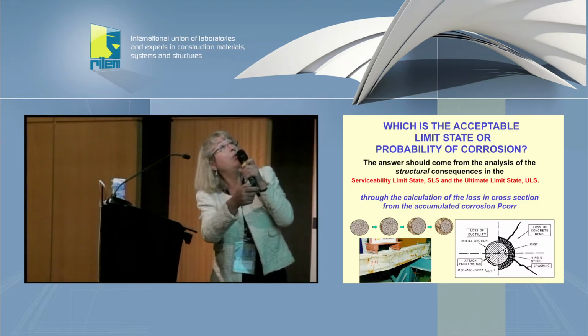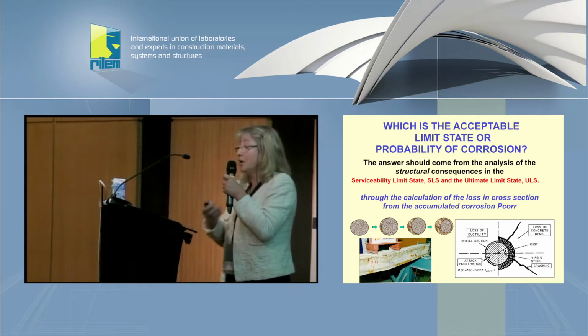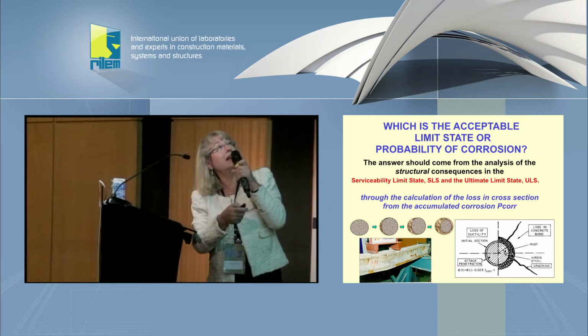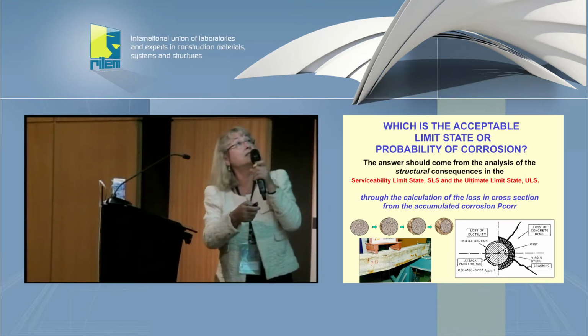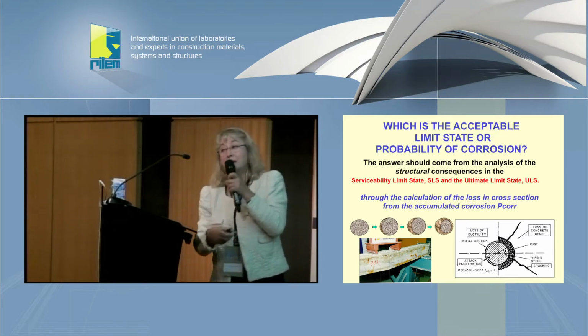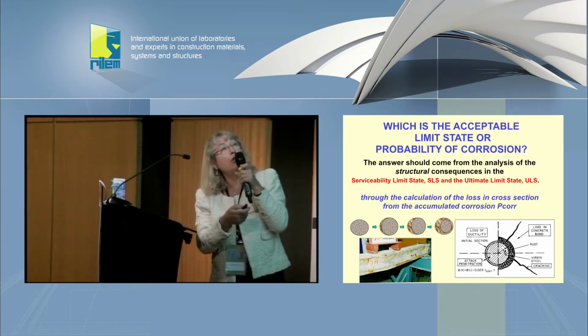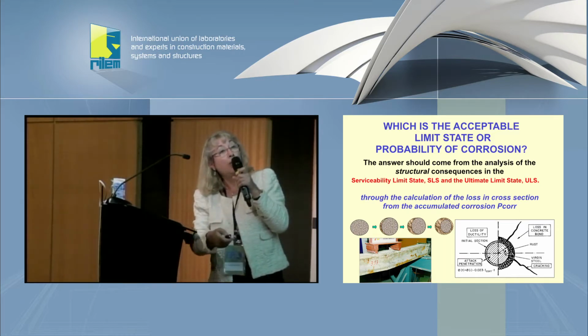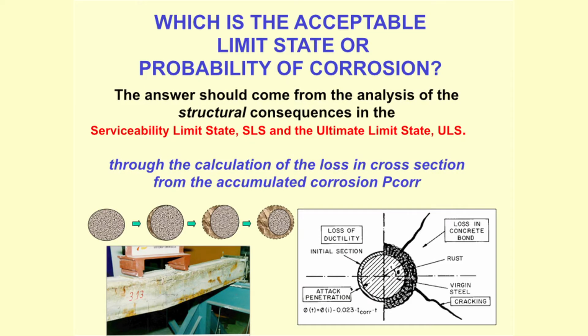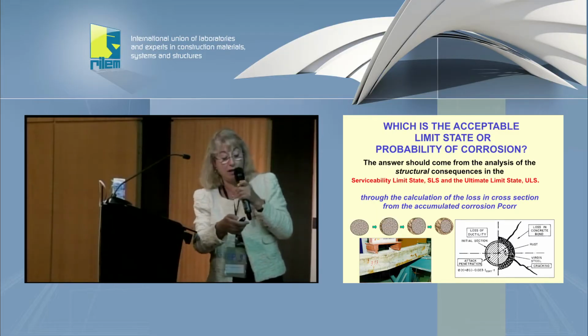Finally, I finish with which is the acceptable limit state for the probability of corrosion, that is another question addressed. In that case, it's necessary to make the structural calculation. You need to verify the serviceability limit state and the ultimate limit state with structural engineers. They need to work with you, at least with me, as I am not structural, in order to calculate the loss in cross-section from the accumulated corrosion. We just link this loss in cross-section with the 4 main consequences of the corrosion for the structural performance, that is the loss of the diameter, the loss of ductility, I will say how important this one is now, the loss in the bond, and the cracking. All those effects have to be analyzed independently and affect the full structural performance of the corroded elements.